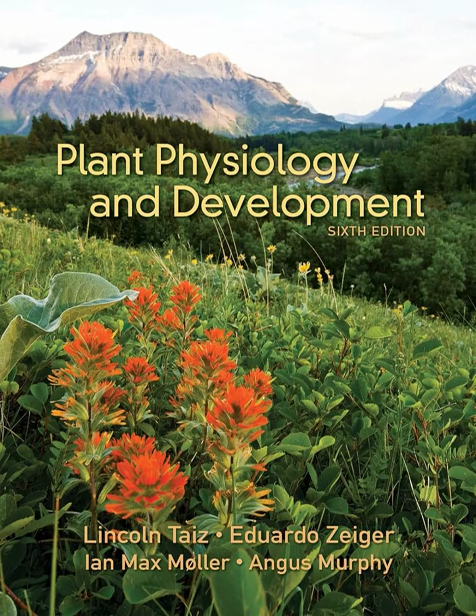And of course, there's often lignin. Right, lignin. Tell us more about that. It sounds crucial for secondary walls. It absolutely is for many types. Lignin is a very complex, irregular polymer made from phenolic building blocks called monolignols. These are synthesized inside the cell and then transported out into the wall. Once in the wall, enzymes like peroxidases and laccases oxidize these monolignols, creating reactive radicals that then randomly link together, forming a large, branched, hydrophobic polymer network.